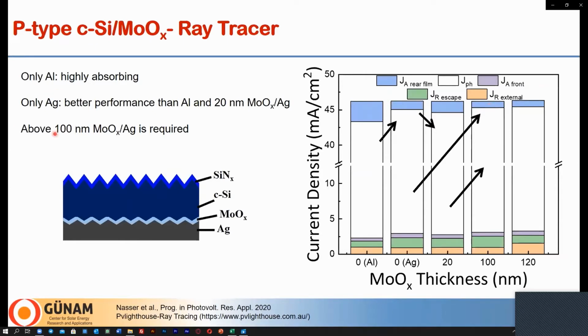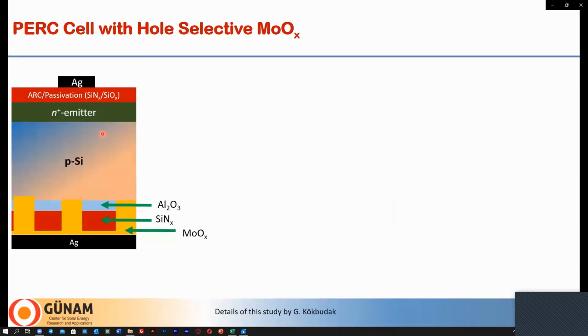However, if you use 100 nanometer molybdenum oxide, experimentally you would get degraded solar cell performance because molybdenum oxide is known to have a high bulk resistivity. So one way to get the maximum benefit is to combine thin molybdenum oxide with low contact resistivity, like 10 or 15 or 20 nanometer, with other dielectric layers in a structure similar to that of PERC. And this is what we did in a different study indeed. So yes, we combined molybdenum oxide with aluminum oxide and silicon nitride in a PERC structure.